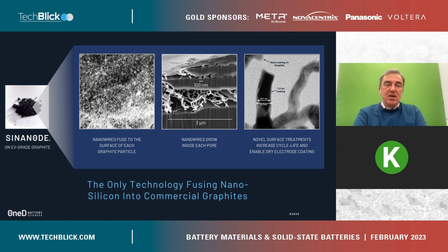They do the hard task of producing 10, 15, 20, 40,000 tons of the graphite. And the graphite can be used as is in these EV cell factories. But when we take that powder and we process it according to the SINANODE manufacturing process, we do something that is quite magical. We add silicon nanowires.